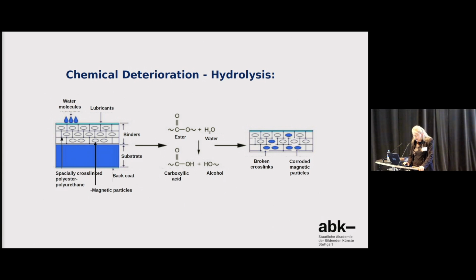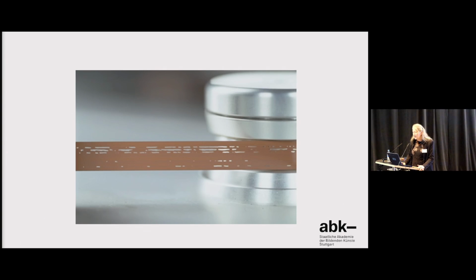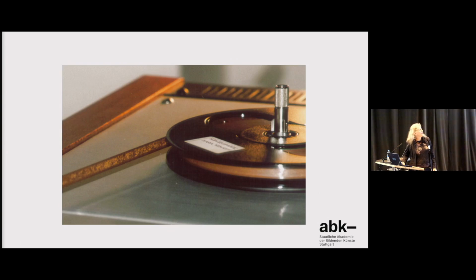So the binders react, in the polyester polyurethane binder, which consists of a hard and a soft segment, esters decompose with water to carboxylic acids and alcohol, and the crosslinks break, and in the worst case, for example, metal particle tapes can also corrode. But you have the chain scission, and the result looks, as we all know, like this, or in a worst case, like this. In this case, the process of delamination, the information on the left side here, where you can look through the tape, is lost because it's sticking on the reel.